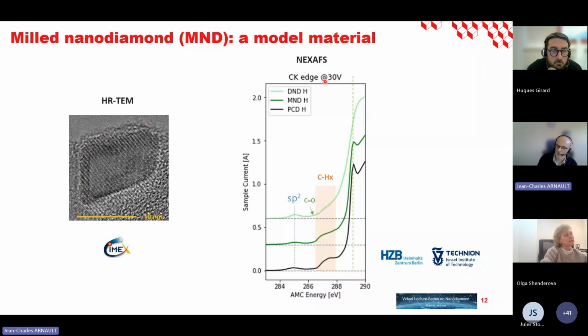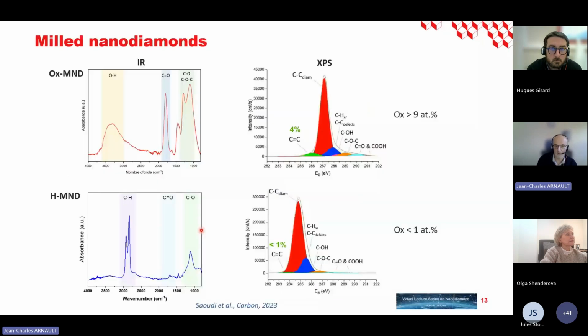And recently, we have done, together with Arsène Chemin, Tristan Petit, and Alan Hoffman, some NEXAFS experiments, comparing different hydrogenated materials: detonation, milled, and polycrystalline. If you look at the carbon K-edge, you can see that for the milled hydrogenated nanodiamonds, we were able to see clearly the diamond exciton, perhaps a little bit lower than that of the polycrystalline, but it's not possible to see it on the detonation hydrogenated particles. So very good crystalline quality, and on such particles, you can also tune the surface chemistry.